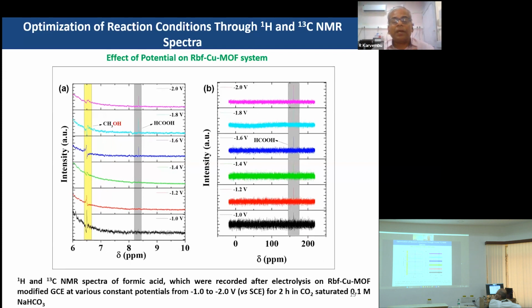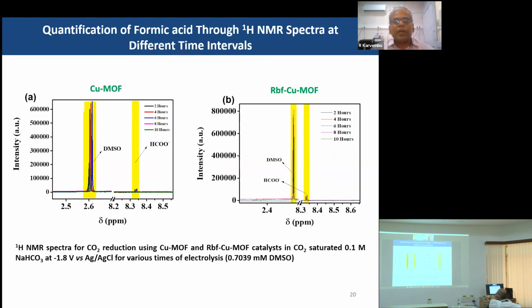These are the spectra obtained when riboflavin modified copper MOF was used as an electrocatalyst for the reduction of carbon dioxide. We quantified the amount of formic acid formed using the NMR technique, in which DMSO was used as an internal standard.